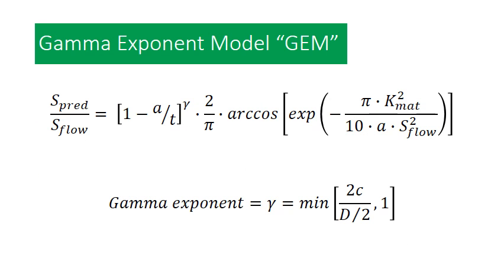Now, for those of you that aren't familiar with some of my other work, I've come up with a failure pressure model, which I call the gamma exponent model. In some ways, it's very similar to the original log secant model from about 50 years ago. But in my case, I've done the derivation based on depth rather than length. I've gone through the entire strip yield model log secant derivation with a focus on depth, and I land on this particular equation. I'm not going to get into the details too much right now, but let's just say that's the equation that I'm going to be working with.